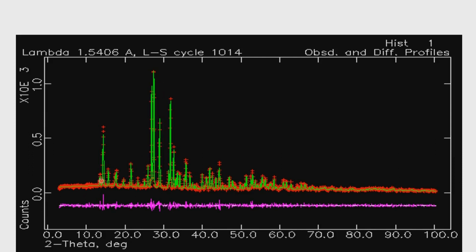So, what did we do in the least squares refinement in the single crystal case? We took the modulus of the observed F HKL minus the calculated F HKL, the modulus, and then we made it a minimum quantity by doing the refinement protocol, and then we calculated an R factor. So, similarly we calculate an R factor here, and that R factor is now associated with the profile. So, we call it the profile R factor.